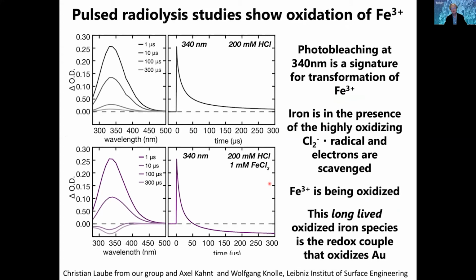So in this case, we've turned to another very classical experiment. We're working now with Axel Kahnt and Wolfgang Knoll at the Leibniz Institute of Surface Engineering in Germany, where they can do pulse radiolysis studies. Perhaps you'll know that if we pass a lot of energetic particles through water, it doesn't really matter if it's electrons or some other kind of fundamental high-energy particle. Almost any of them passing through water will create more or less the same chemical environment after a little while. So we can use, at a bulk scale, pulsed radiolysis to probe what happens inside a liquid environment of water when we add different chemical species. And one of the things that we can see very clearly in those kinds of experiments is the presence of a very strong photobleaching at 340 nanometers.